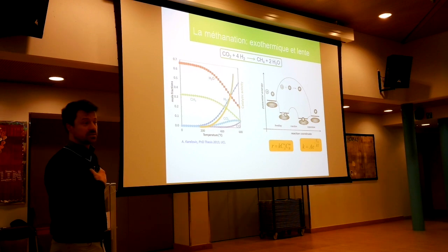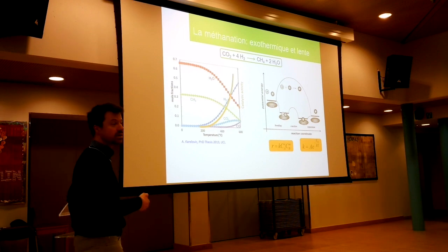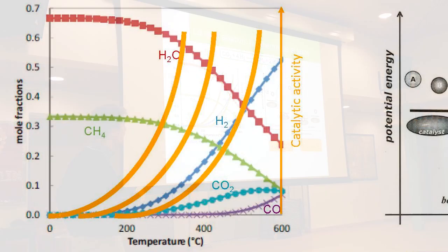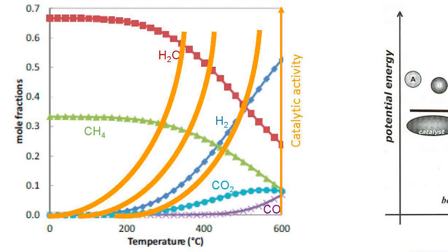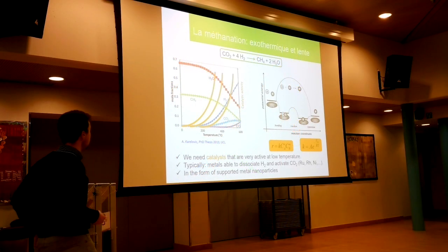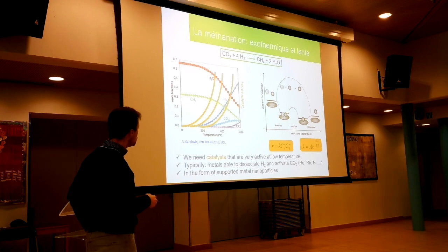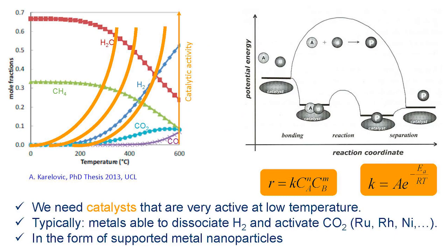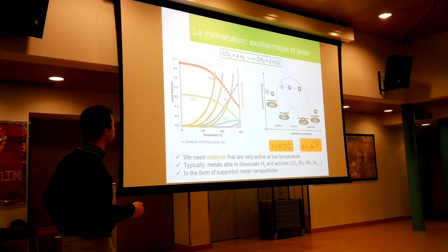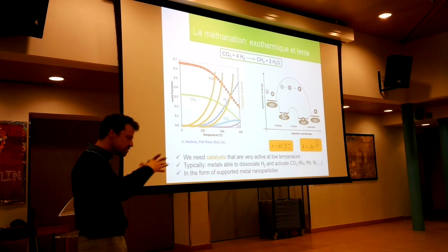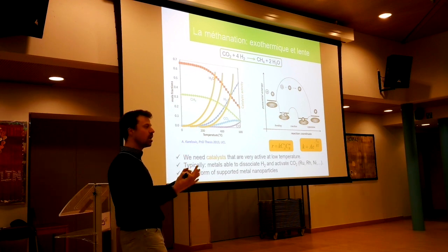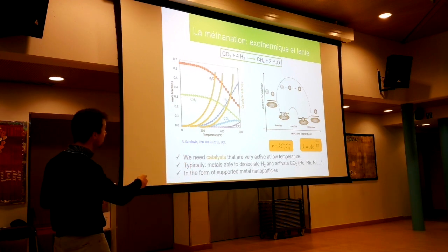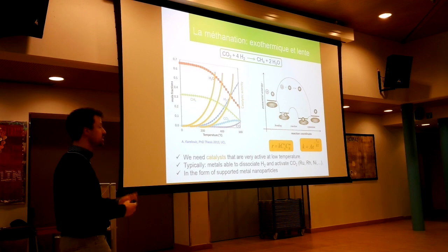Our job as catalysis scientists is to find the right catalyst, and the right catalyst in this case is a catalyst that will be active at low temperature, as low as possible, because we are dealing with an exothermic reaction. So what we do is to develop those catalysts. They are typically based on noble metals like rhodium, ruthenium, nickel. Nickel is not noble, but those kind of hydrogenating metals. And our job is also to disperse them, to have small nanoparticles, to have a large active phase. So a lot of surface sites for adsorption, dissociation, and reaction.